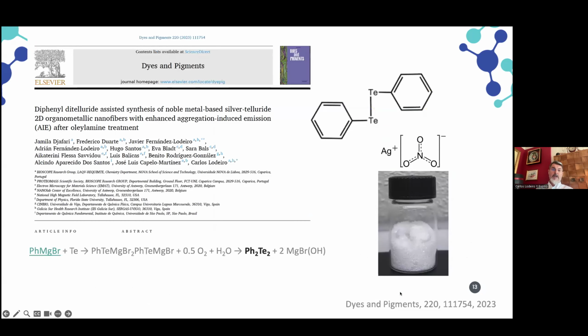For example, I selected this paper to show you just because it was a surprise for us. We were using an organic molecule, diphenyl ditelluride, a very simple one, in order to create silver nanoparticles. We have a collaboration with the University of São Paulo in Brazil, where there is a very strong group in the development of different chalcogenide materials, especially devoted to selenium and tellurium. When we mix it with a silver solution, for example silver nitrate, we create a material that doesn't emit light.